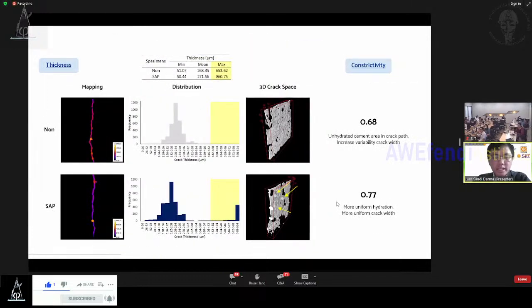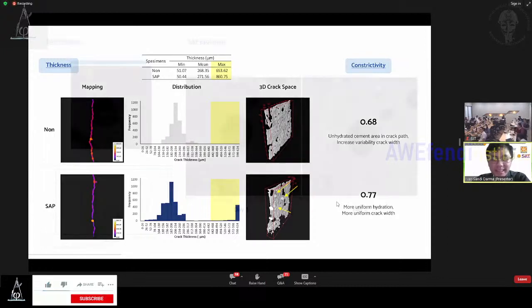Through X-ray CT, we can also observe crack geometry properties like distribution and connectivity. The distribution is similar, but the maximum thickness of the SAP specimen is attributed to the pre-soaked SAP being bigger when it absorbs water. And from the 3-dimensional crack space, connectivity can be quantified. The SAP specimen has a connectivity value closer to 1 than the non-SAP specimen, because uniform hydration makes more uniform crack width.